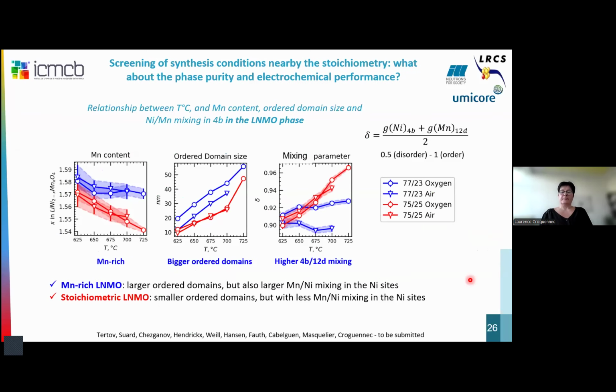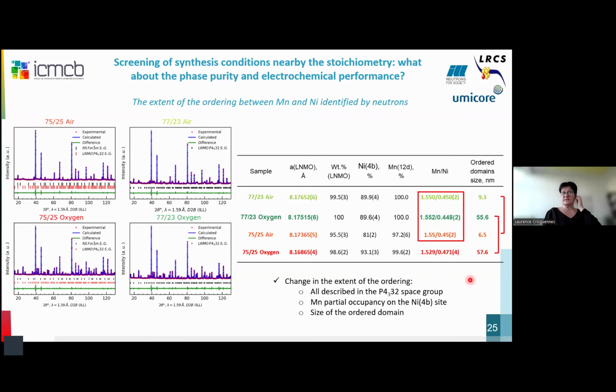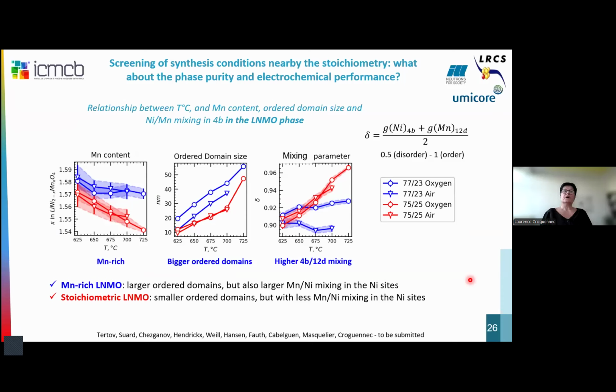So that was for given synthesis compositions, playing with the compositions of the materials. But now what happens if we take these manganese-rich materials obtained under air, and do the thermal treatment at different temperatures, here moving from 625 degrees to 725 degrees? How do these parameters evolve? Do we always have the same tendencies? I will not show here the electrochemical performance, but we have really the same tendencies.